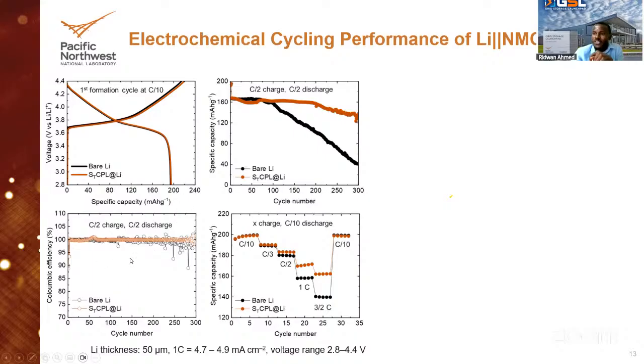And this one is just showing the efficiency here, which is about 100% for the protected lithium. And if you look at this black line here, that is for the bare lithium. That is also close to 100%, but it's fluctuating, and it's still lower than that of the protected lithium.